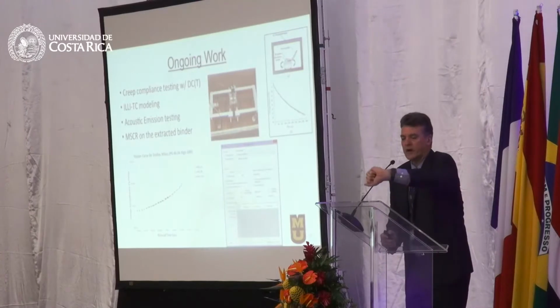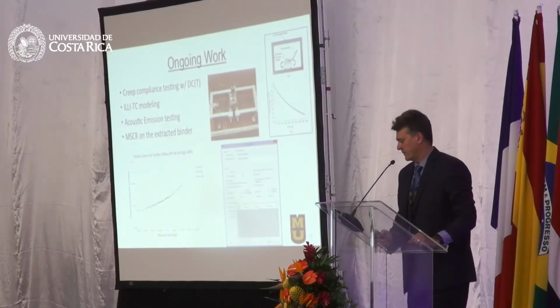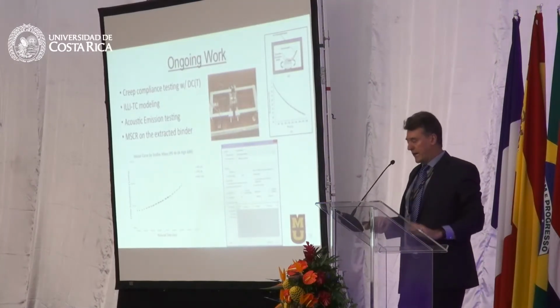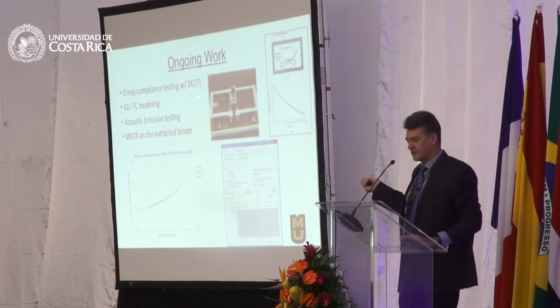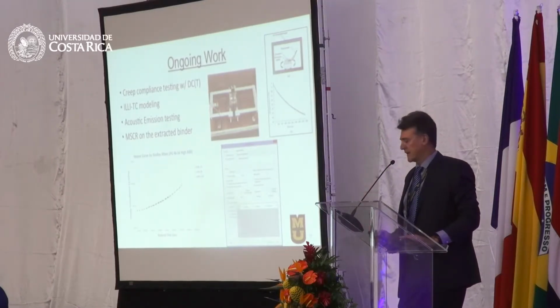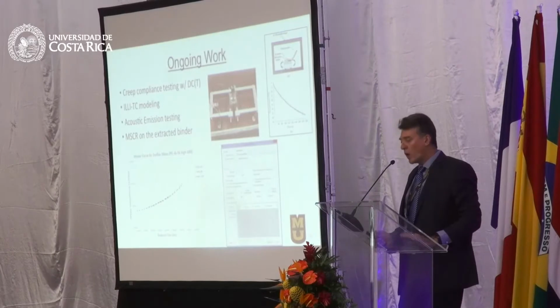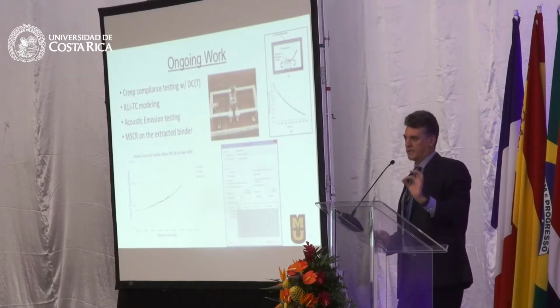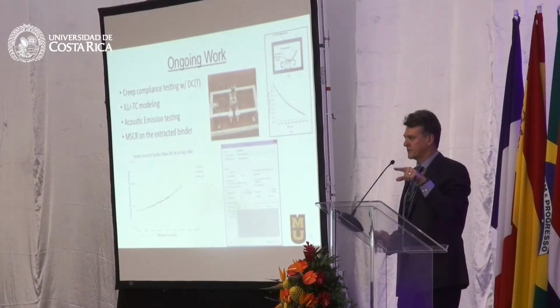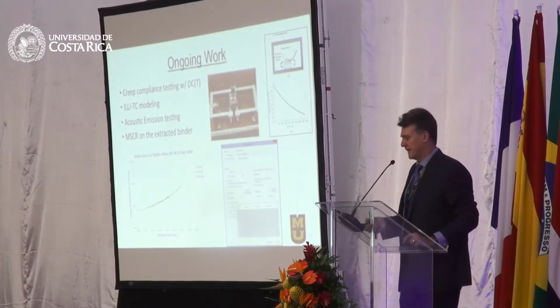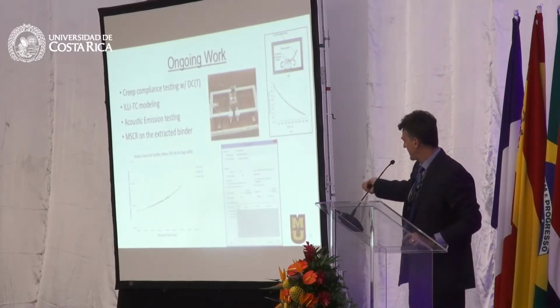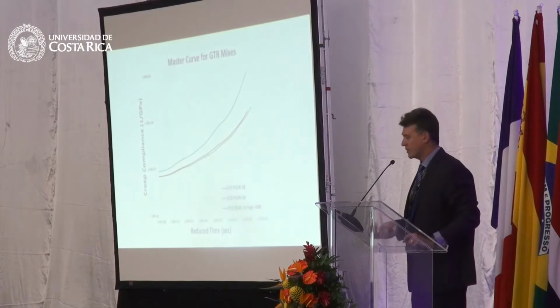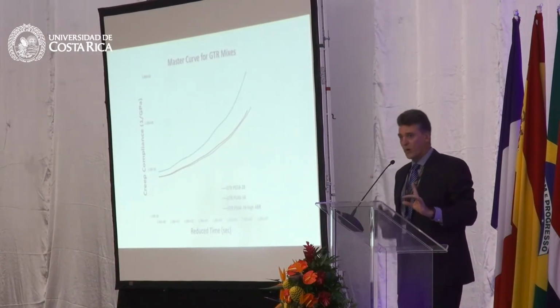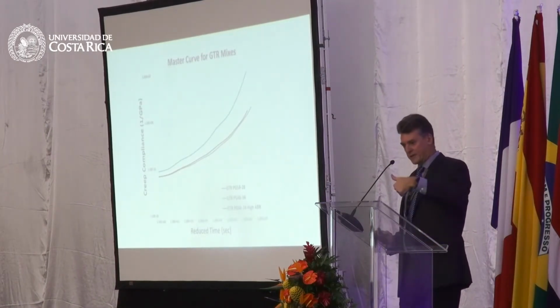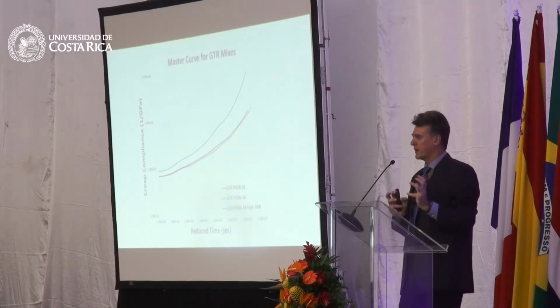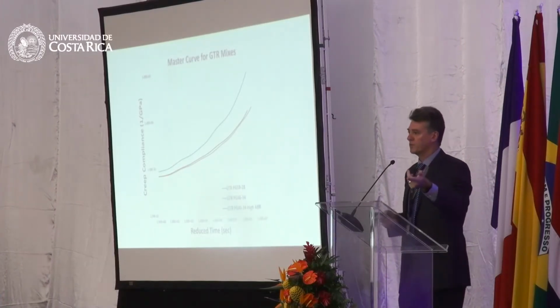So we have a little bit of ongoing work, and one is creep compliance testing with the DCT test, and also that thermal cracking modeling that I spoke about before. We wondered if we could do a fixed load test on this fracture geometry prior to fracture testing. These are the type of creep compliance master curves that we get. I was also wondering if the same trends in fracture energy, when we rip the specimen apart, would be seen in the rheological mixture test.